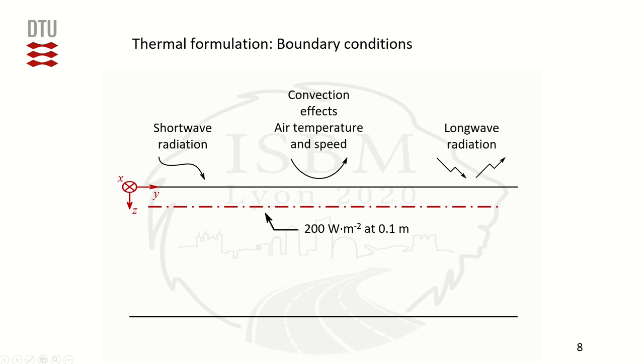The considered heating system aims at representing an array of ribbons embedded at a depth of 10 cm into the medium, each ribbon being spaced 20 cm from each other, center to center. Each ribbon has a power of 40 watts per linear meter, which results in an average output power of 200 watts per square meter in the one-dimensional model. A fixed temperature of 10 degrees Celsius at a fixed depth of 1.5 meter serves as a lower boundary.